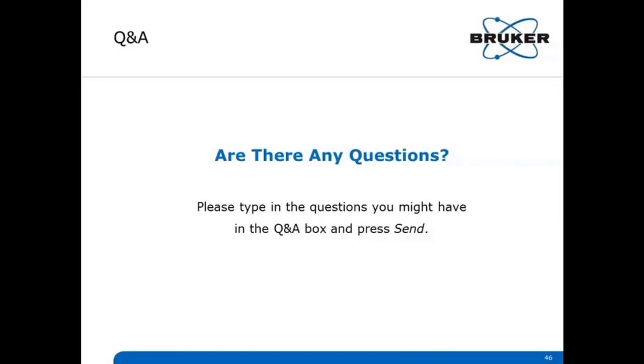If you just want it qualitatively, you don't need any standards. So what we have seen during this webinar was just qualitative. We did range scans. So we were just looking if the elements or the peaks were present. So therefore, you don't need any standards. Or for mapping qualitatively, like what we did, we just set the mapping energy on the peak, and we mapped it just to see if the elements are present or not. So therefore, we don't need any standards. But if we would like to quantify the map, which is clearly possible, then we would need a second measurement also for the background position, not only the peak position, and we would need standards.